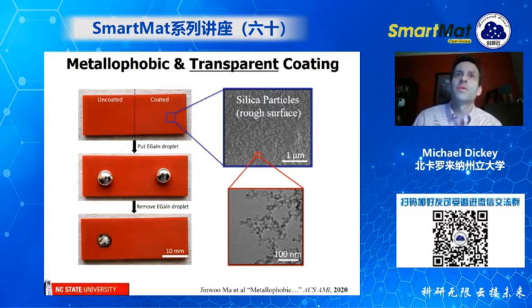If you put liquid metal on both sides, you'll see that on the uncoated side, the metal sticks, but on the coated side, you can pull it right off. And if you look at this coating, you can see it's got these silica particles, and it makes this rough surface, which you can see are a few nanometers in size.